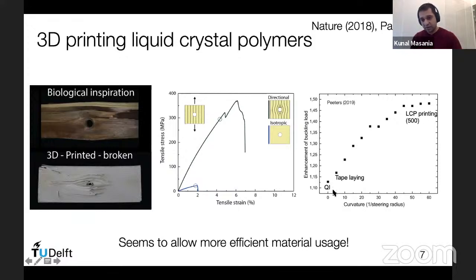And I also indicated here below typically what happens with quasi-isotropic laminates or for tape laying, which is today current state of the art. And what we notice is with LCPs, you have a much higher shaping freedom. So you have a curvature of 500, which is way off the chart in this case. And it seems to indicate that even though we have a less performant raw material, just by having more shaping ability, we can take on other types of application where traditionally we were using more energy intensive materials. So this kind of leads to the idea of being frugal with the material we have, using it only where we need it in the right orientation, and therefore using resources to a much lesser extent.